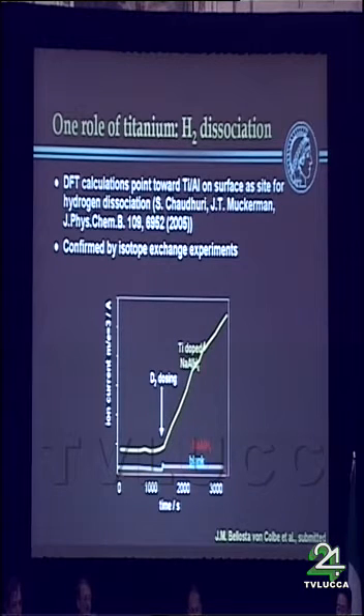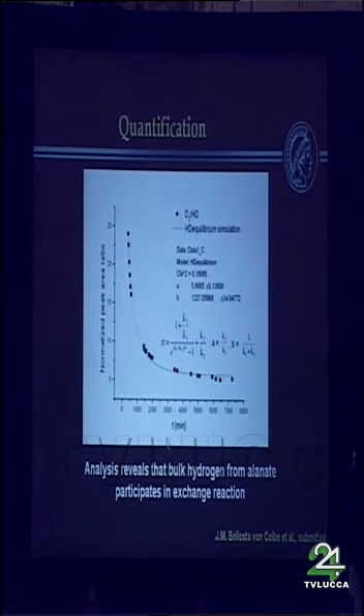If we put sodium alanate in a deuterium environment, there is no scrambling, there is no HD formed. But if we put titanium-doped sodium alanate in a deuterium environment, we find HD in the gas phase, as seen here. After D2 dosing, we find HD in the gas phase. We have looked at this in more detail, calibrated the volumes, calibrated the amounts, and fitted kinetically. If we analyze the data, this is an experiment at 60 centigrade, the result is that basically at 60 centigrade, the hydrogen from the bulk of the sodium alanate participates in the scrambling experiment.